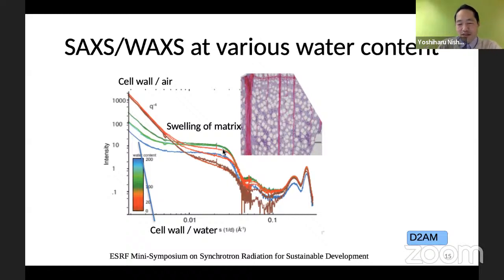So here what we see, using the small angle scattering region, is the swelling at the nanometer scale, which is pushing the whole cell wall and which generates the power to fracture the rocks. At a high angle, here in this high Q range where we see the crystalline region, this doesn't change with the hydration because water is not penetrating the crystal.